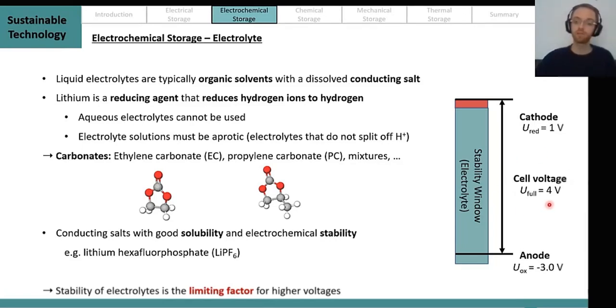So we are now at a cell voltage of 4 volt. But our cathode electrochemical potential will lie outside this stability window, and this means that we will continuously degrade our electrolyte, and we will not be able to statically store charges in our system, provided that certain other requirements are not setting in, like our cathode, for example, being passivated or else. So the key issue here is simply that once you leave the stability window of the electrolyte, there's the risk that you're simply not able to store energy anymore, but you will rather simply degrade your electrolyte in the process.